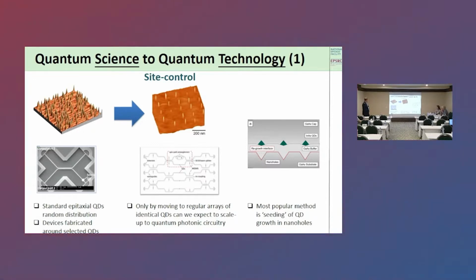We are able to do this, but only with one or two quantum dots. We want to be able to do it with tens, hundreds, thousands of dots. The usual way is seeding, as has been explained. So you basically create a nanoscale structure here, and you want the quantum dots to actually form in these nanoscale structures and not in between, and that gives you this kind of regular ordering.